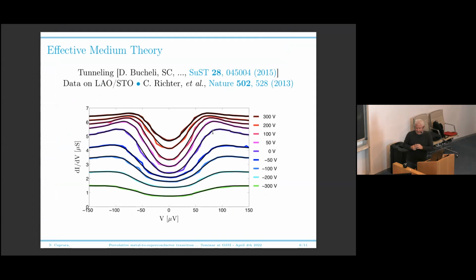We were interested in tunneling spectra. Again, the colored curves are the data, and the lines are our fits with effective medium theory. What was striking about this, the curves are displaced vertically for a better view. But I can tell you that what is striking in all these curves is that there is a very large value of the tunneling conductance. This is the differential tunneling conductance.